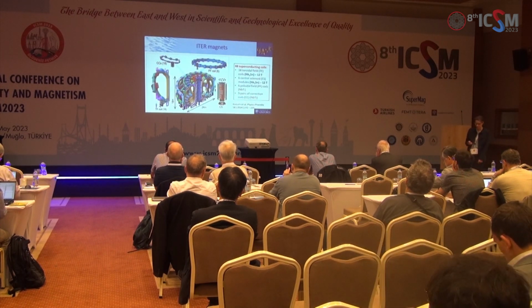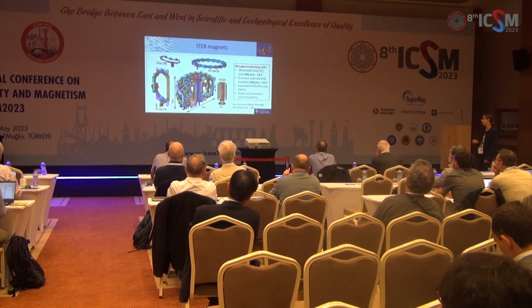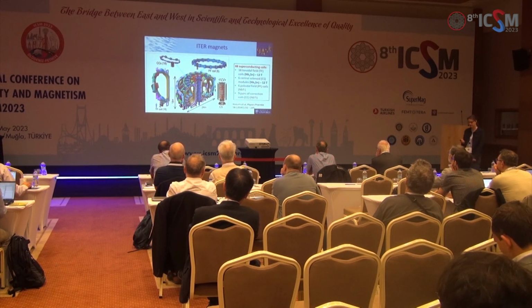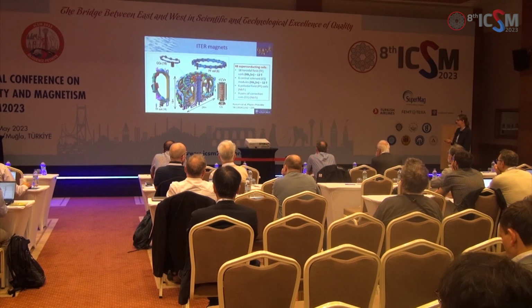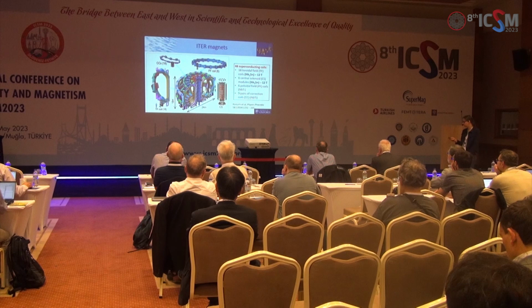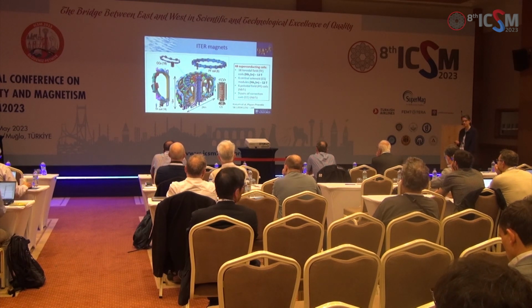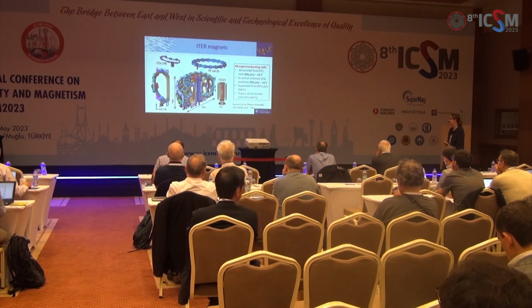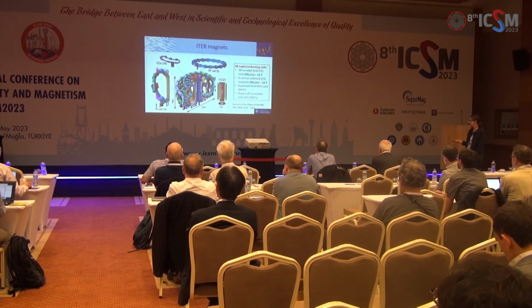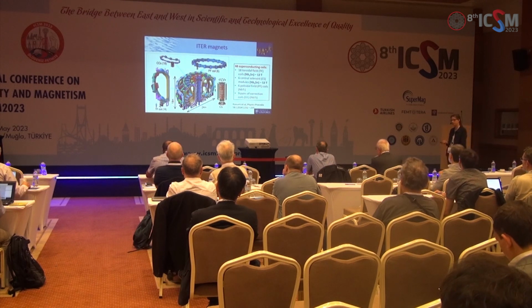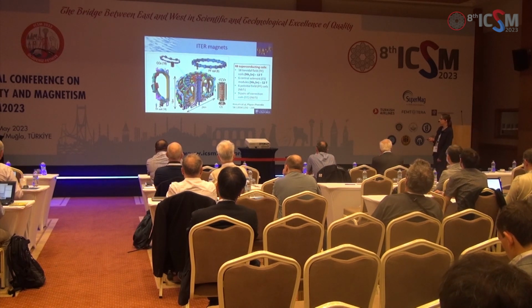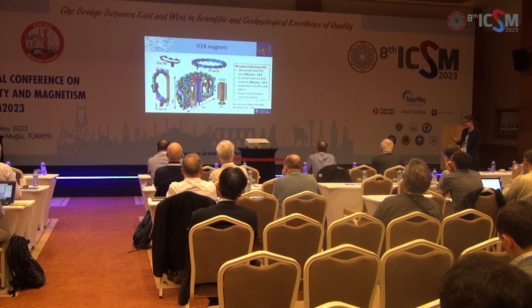So ITER, which is being built in the south of France at the moment and has been in design since the late 1980s. This is a superconducting fusion device. It has 18 toroidal field coils. These are the D-shaped coils here, which essentially do the main bit of the confinement of the plasma. They need to work at about 12 Tesla, so niobium titanium wouldn't work, so niobium-3 tin has been used instead. We have other important components like the central solenoid, which is also very high field and uses niobium-3 tin. The other coils in there use niobium titanium.